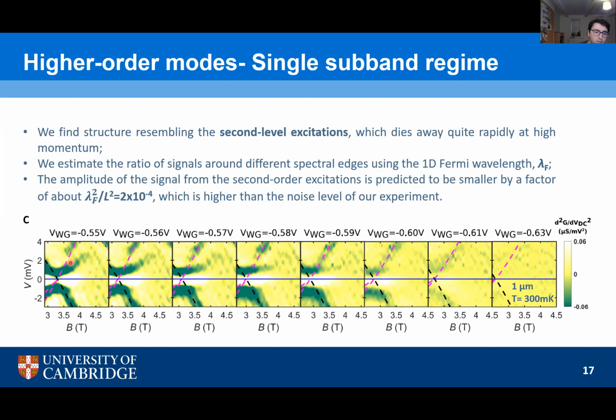As one last thing in this data, if you look carefully at negative bias, there's a kink here. This wouldn't be cause for much, warranted only observed for 1 micron devices. Two replicas are clearly visible, but if you want to be optimistic, this could be evidence of a third replica as a shadow band to the second level replica. It seems to show some response to the Y-gate. Of course, to be sure, we would have to go to submicron lengths, which we haven't done yet. But once you go submicron, at some point you need to ask yourself, when does it stop being a quantum wire and become a QPC? Anyway, two replicas in the data seem to emerge as a function of length.